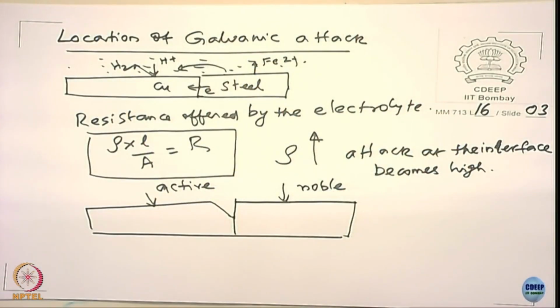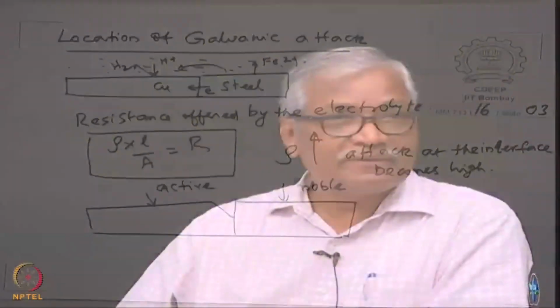The characteristics of corrosion failure is, it happens with the active metal, it happens more at the interface. If it happens, for example, at the noble metal, you would not call it galvanic corrosion. Maybe erosion has taken place. Metal may be noble but is softer, so it happened. Maybe there is some microbial corrosion taking place.